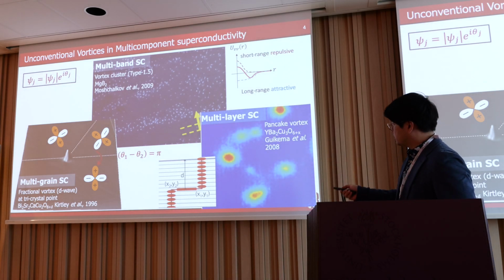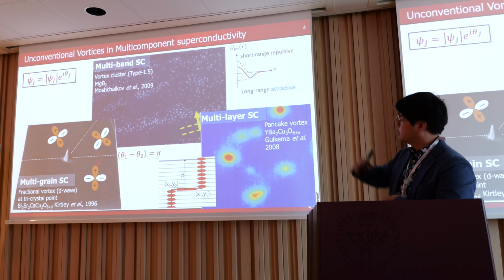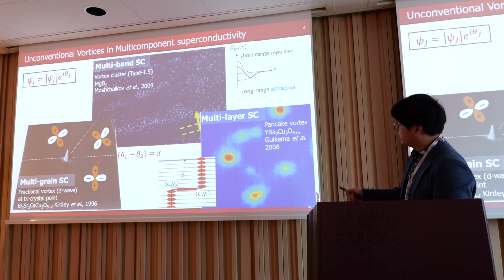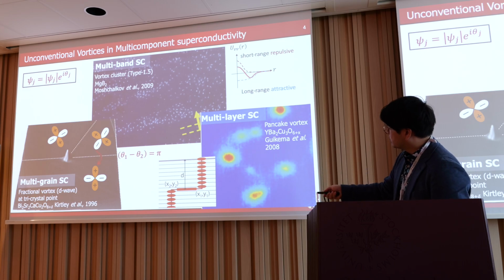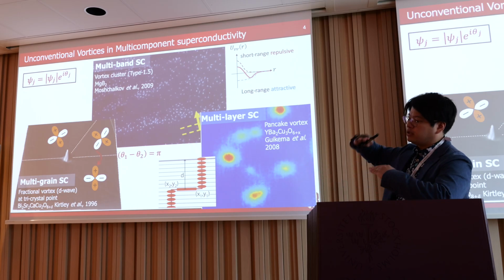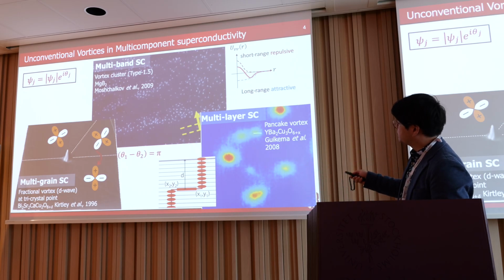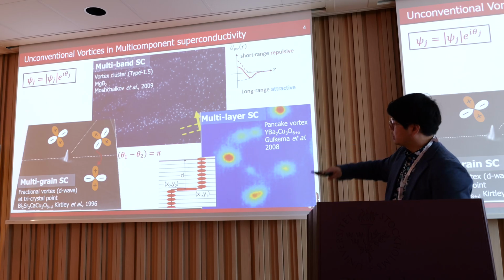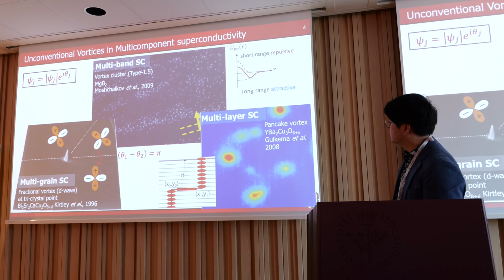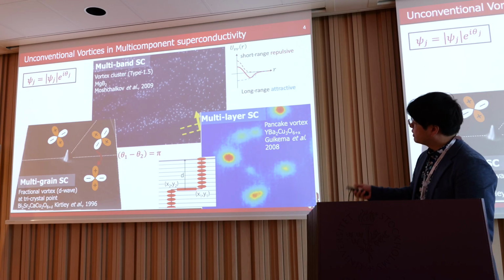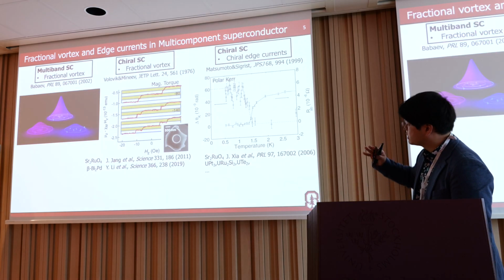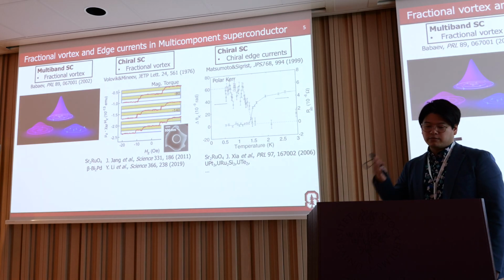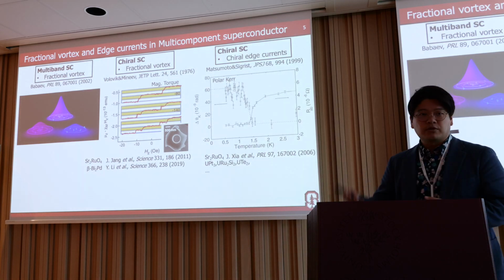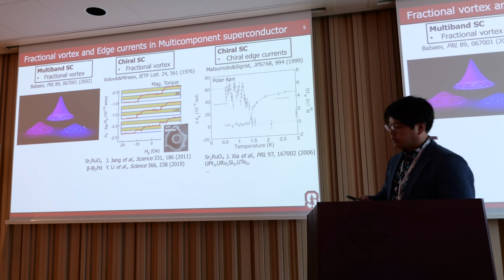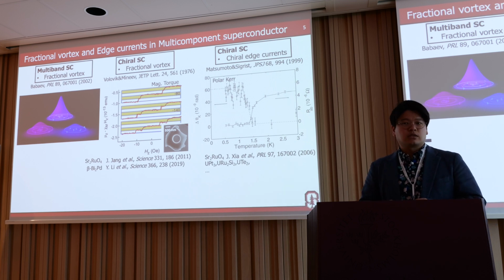And okay, this is a highly anisotropic layered superconductor, the cuprate case. And it splits the vortex like this. So it's randomly split because it's very highly anisotropic. It's easy to split by applying the local field, like a scanning Hall or scanning SQUID microscope. It only happens in very highly anisotropic samples. But in theory, they expect more fractional vortex or magnetic phenomena in the multicomponent superconductor.